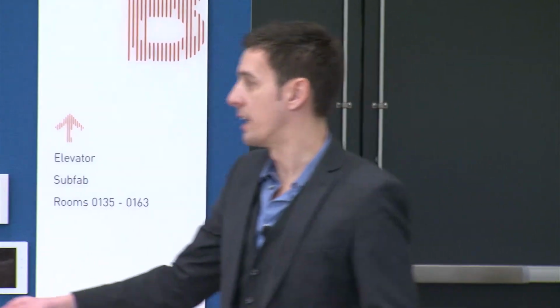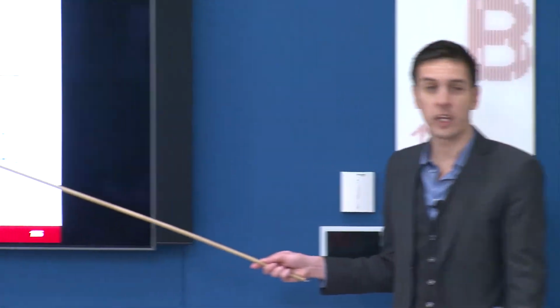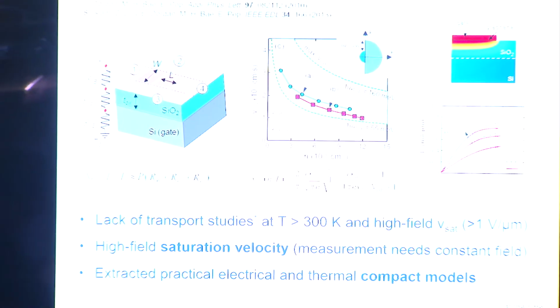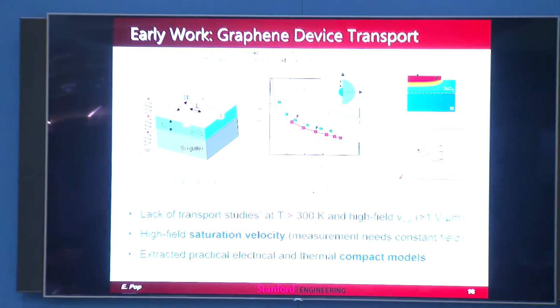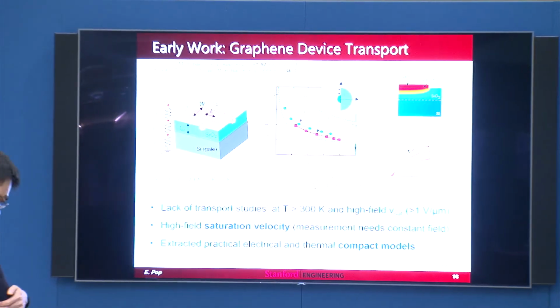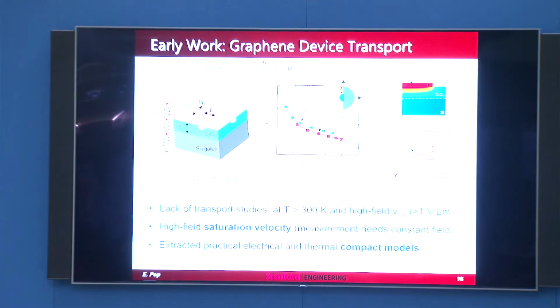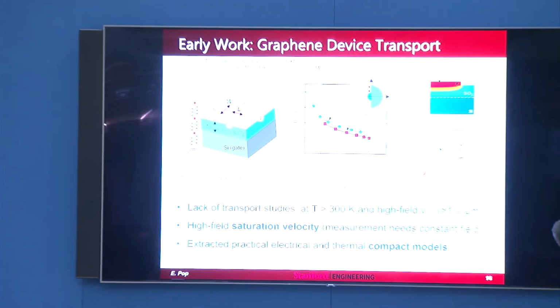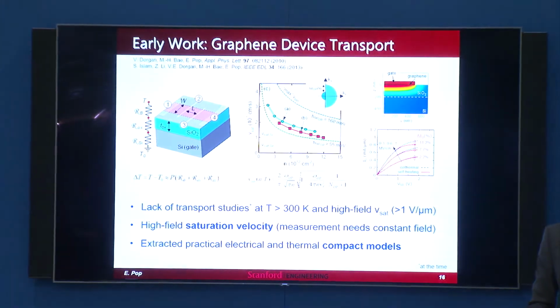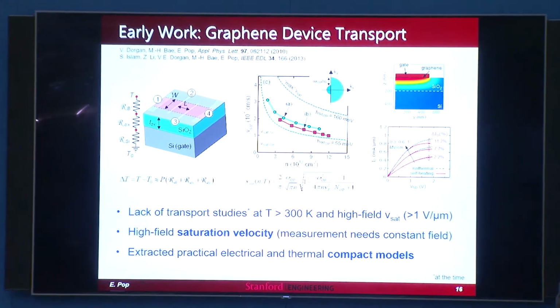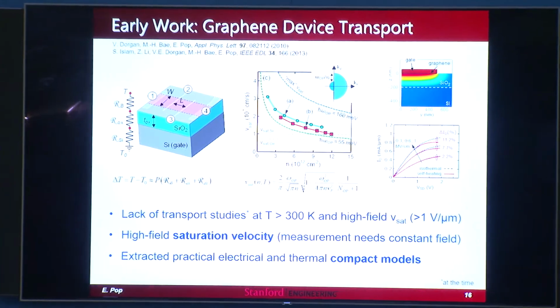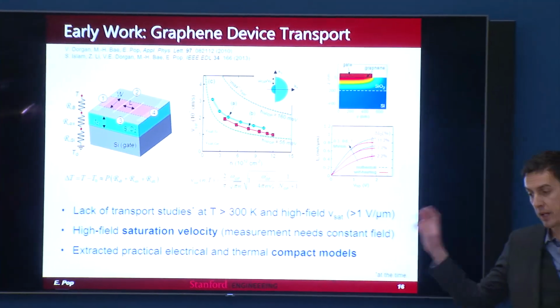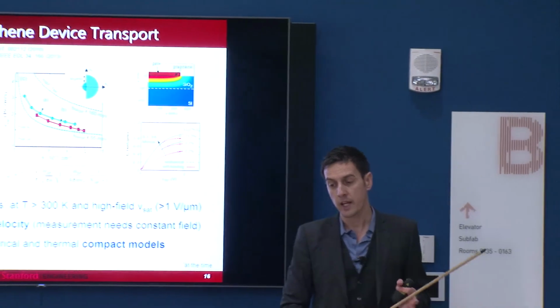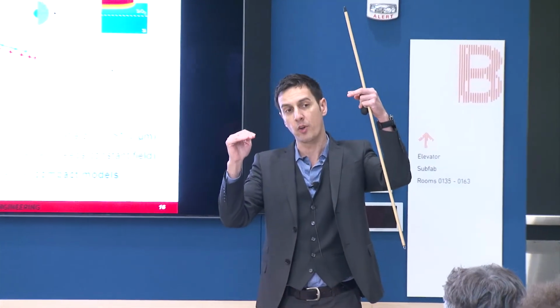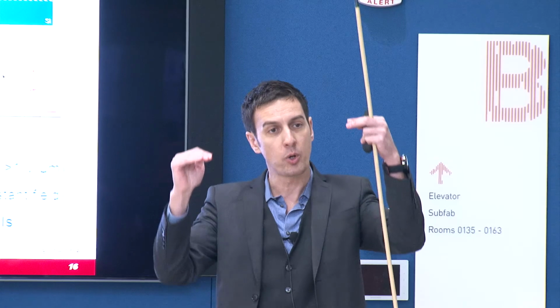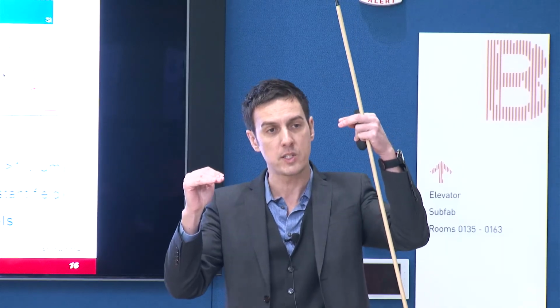So you notice that this is a tricky thing. You really need constant field across the device, because if you're actually biasing it in the real saturation regime of the transistor, you're going to have pinch off over here, and so you're going to have a very, very different carrier density and velocity profile. So we struggled with that, and we really have to bias them the right way. And in our papers, we state that the carrier density from source to drain, we try to keep it varying no more than about 10%. So we put upper limits on how much we're willing to vary the carrier density.